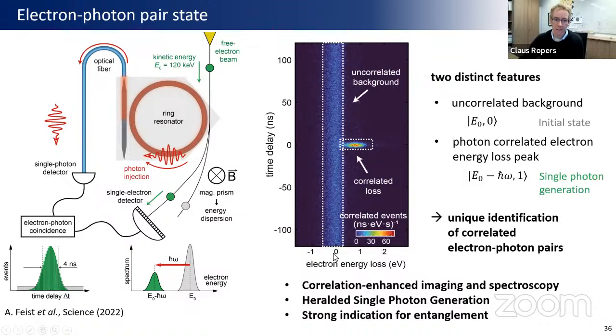Yeah? So what we see here is basically a range of uncorrelated background electrons not having lost energy. So those are just electrons which have not scattered at the resonator, have not produced a photon. But at zero time delay, in this coincidence experiment, we see a strong peak of correlated events, which correspond to electrons having lost one photon energy and a photon detector having detected that very photon. Yeah. What this means is this is a correlation experiment, coincidence experiment of a single electron producing a single photon, essentially.